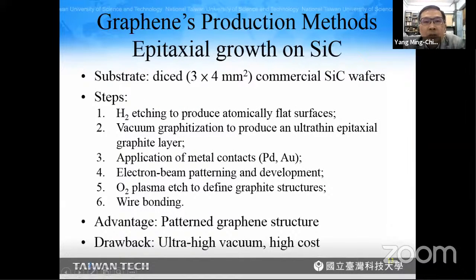The other type of bottom-up process is epitaxial growth on silicon carbide. The substrate used is commercial silicon carbide wafers. In the first step, hydrogen etching is used to produce an atomically flat surface. In the second step, vacuum graphitization is used to produce an ultra thin epitaxial graphite layer.